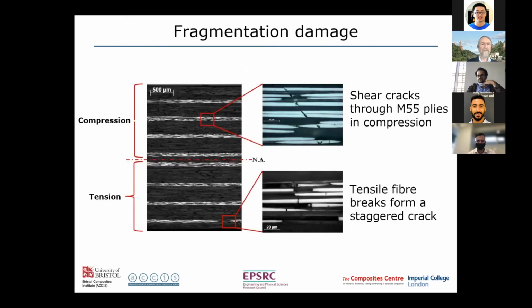If you look at the specimen afterwards, you'll see on the compression side, we have these characteristic angled cracks, which look like shear cracks going through the ply. If you look at the tension, we get quite a different type of response, because there we have the tensile fiber breaks, and they don't all line up. So different fibers are broken in slightly different places, but they're still relatively close together and can interact to form some sort of staggered crack.